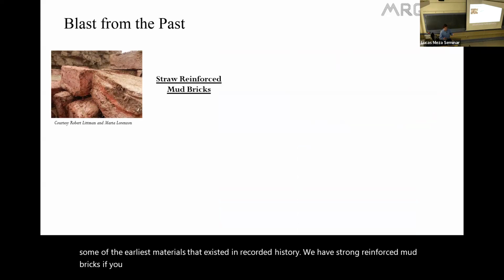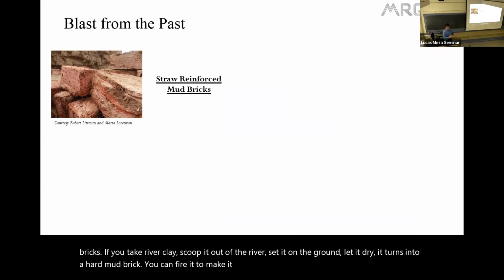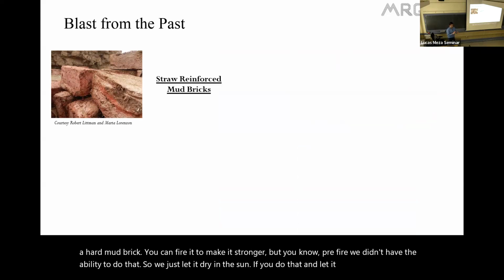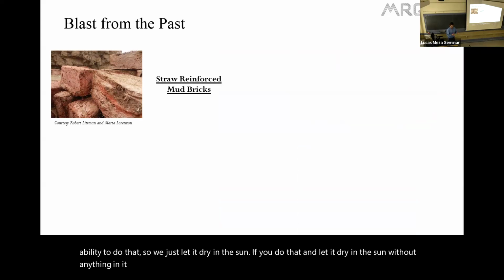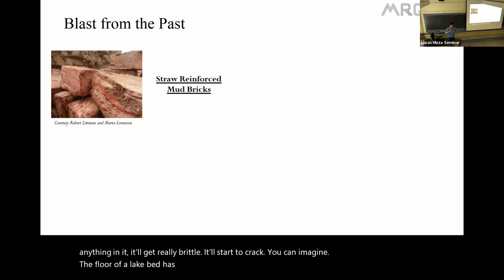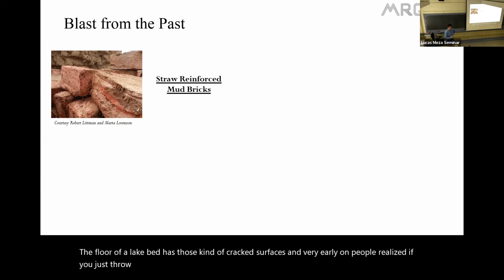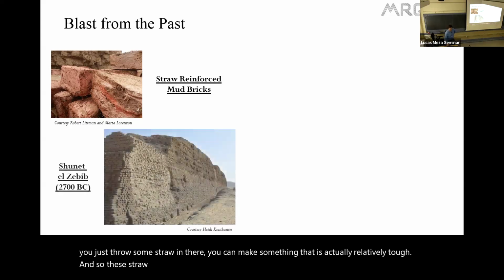If you take river clay, scoop it out of the river, set it on the ground, let it dry, it turns into a hard mud brick. You can fire it to make it stronger, but pre-fire, we didn't have the ability to do that. So we just let it dry in the sun. If you do that and let it dry in the sun without anything in it, it'll get really brittle. It'll start to crack. You can imagine the floor of a lake bed has those kind of cracked surfaces. And very early on, people realized if you just throw some straw in there, you can make something that is actually relatively tough. And so these straw reinforced mud bricks were used in engineering thousands of years ago.